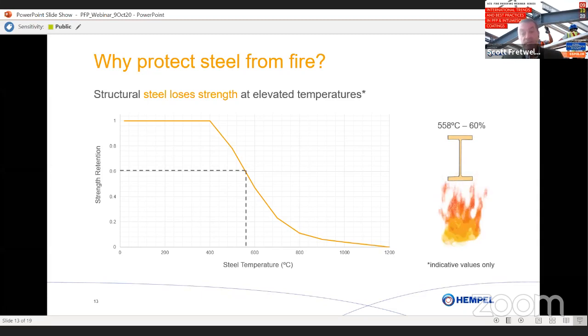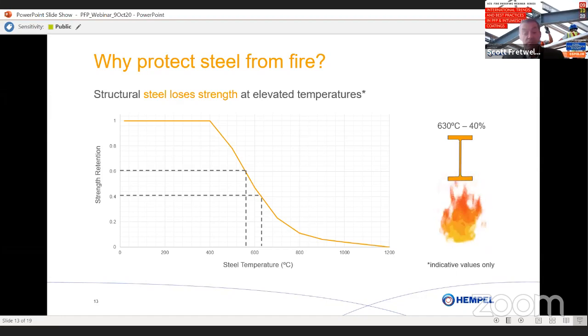However, if there was a fire, we can see around 550 degrees C, the steel profile would have lost around 40% of its strength. If the steel continues to increase in temperature, in this case 630 degrees C, you can see now it would have lost around 60% of its strength.